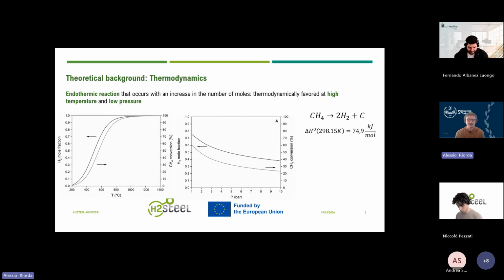As you can see here, the methane cracking reaction is a reaction where the methane is just decomposed into gaseous hydrogen and solid carbon. And this is an endothermic reaction. It means, of course, that you need to give energy to the methane to then crack into hydrogen. And as you can see in the first plot on the left, it means that you need a higher temperature to have a good conversion of the methane. So if you increase the temperature, you're increasing the conversion of the methane.